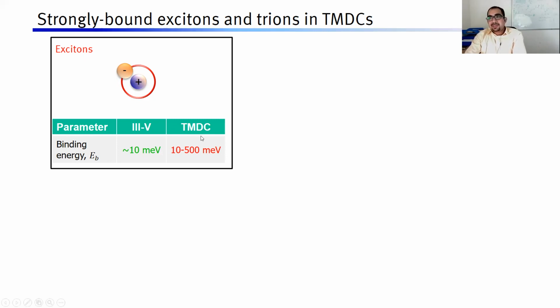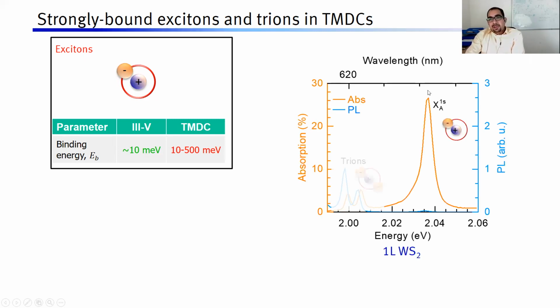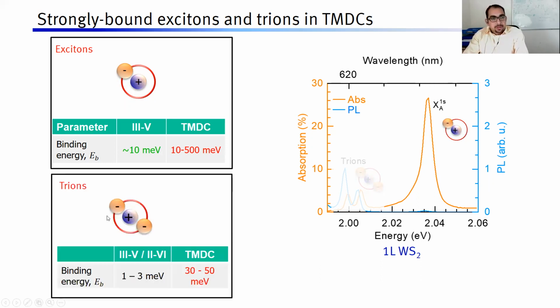So one can easily expect to see these excitons at room temperature, compared to the III-V semiconductors such as gallium arsenide. An example is shown here for a single layer of tungsten disulfide. This is the absorption spectrum, and this is a very strong excitonic peak. At this energy, a single layer of a material is absorbing almost 30% of light that's shining on it. This is incredible to me. Just a single layer, which is 100,000 times thinner than human hair.